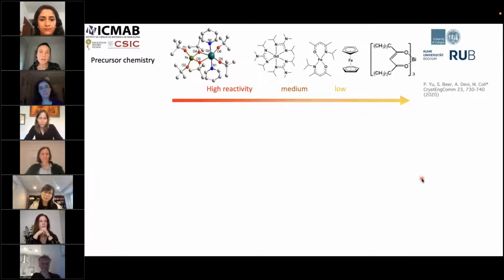So at this stage, you are aware of the relevance of the precursor chemistry. So it's very important what controls the final quality of the film is if we have one metal or two in the complex. If this metal is surrounded only by nitrogen or oxygen and nitrogen, this modifies the reactivity and of course the stoichiometry, the crystallinity, the phase purity.